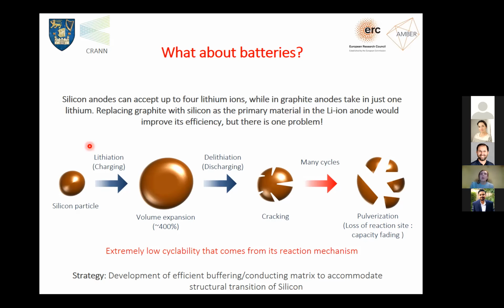The problem there, as everyone knows, working with silicon nanoparticles for battery application, is that when you charge and discharge the anode material, you actually also have a volumetric expansion and then compression of about 400 times. So the volume really changes drastically. And this causes cracking and then eventually pulverization after a few cycles. And despite silicon being a very, very good anodic material for lithium-ion batteries for its theoretical capacitance, it's really not a pursued strategy for the battery field because of this very problem.